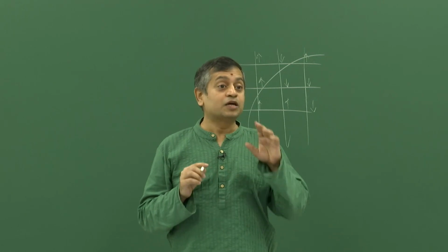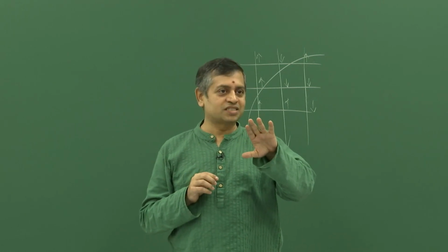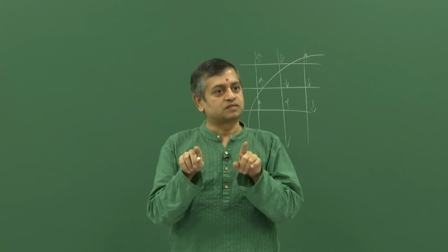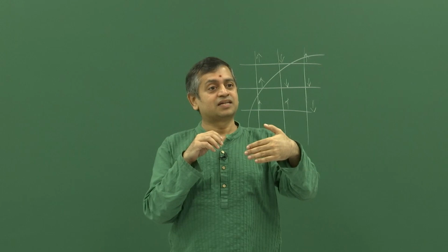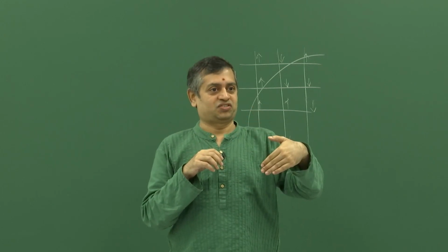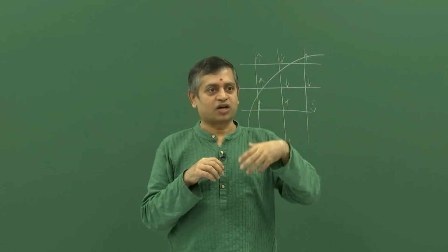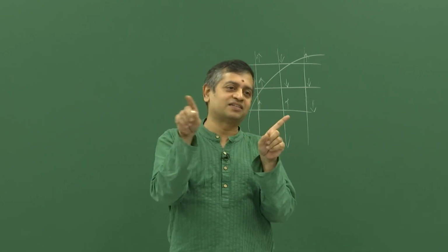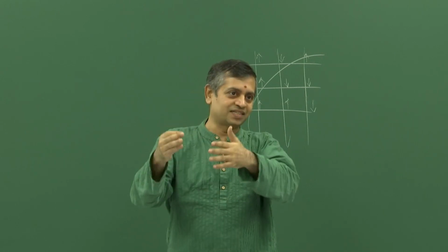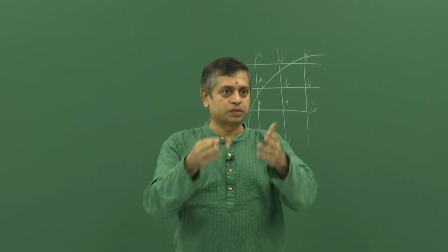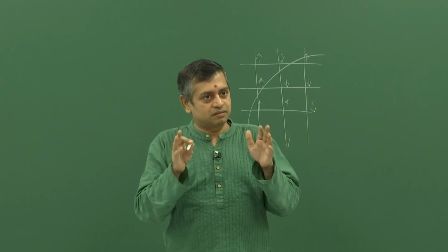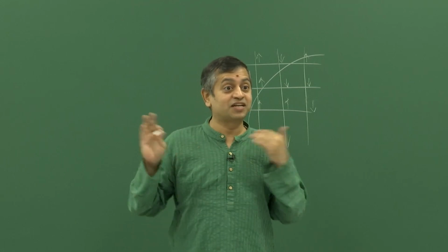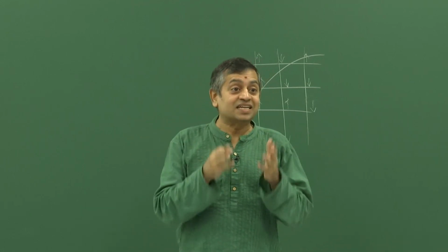That would be my feeling, provided, you see, that also is tricky in the sense that we are not distinguishing the orientations. We are not giving the grain boundary what type of boundary it is. There is a way to put all that in by hand. You can identify orientation 1 is this, so between 1 and 3 I will have this boundary energy and this boundary mobility and so on. People do put that in, then you will get something which is realistic. But if everything is isotropic, okay, it is a soap bubble, fine, it will work. But that is not the real case.